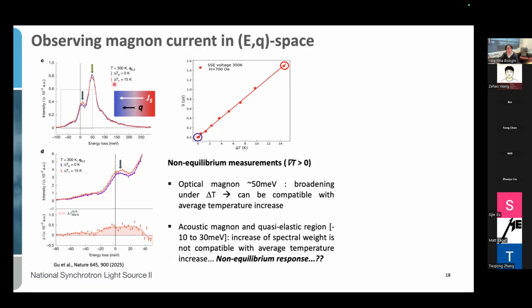If we look at our spectra closely, we may notice that as a function of temperature gradient, we have two regions in the spectrum that are changing. The first change is around the optical magnon region, around 50 meV, and we notice a dampening here as we increase the temperature gradient across the sample. But this magnon dampening can be explained by an average increase of temperature.